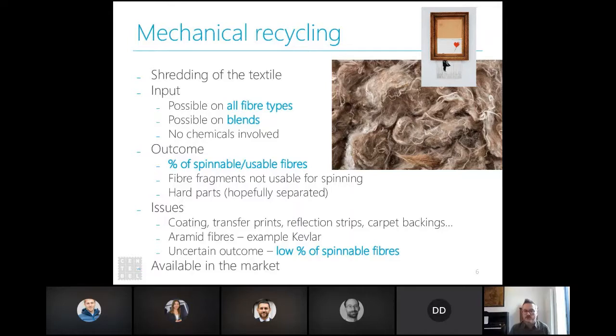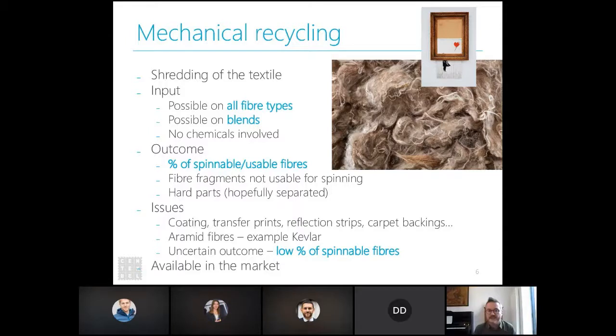So when it comes to nonwovens for insulation materials, also coatings and so on, it is not an issue. But to really gain fibers to spin a yarn again, for jeans there's only about 10% of fibers coming out of a jeans pair that you can use within a spinning production again. So there are a lot of fiber fragments that are not usable for spinning, and also hard parts that are hopefully separated come out of it.